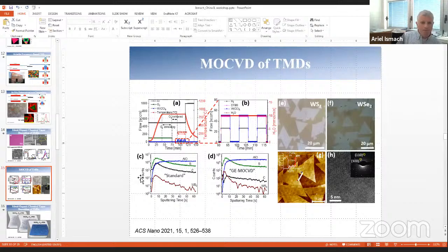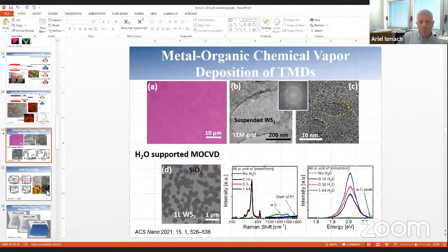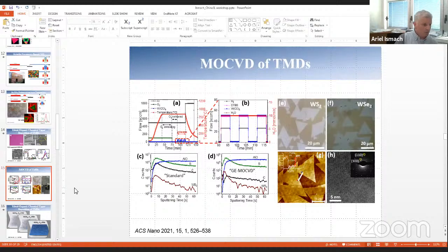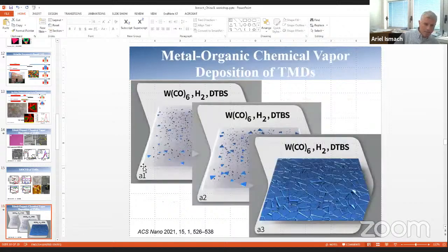And then we can show that if we move on and implement a sequential growth in which we grow and we etch, by pulses, we can increase the domain size dramatically, which is again an indication of crystallinity. Now you can see the atomic resolution TEM images, and also the domain size in the range of tens of microns, and also, of course, PL and many other techniques. And the idea behind that is that, okay, I will explain the idea here.